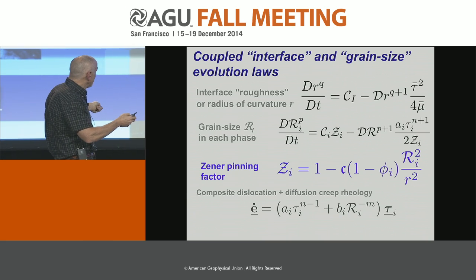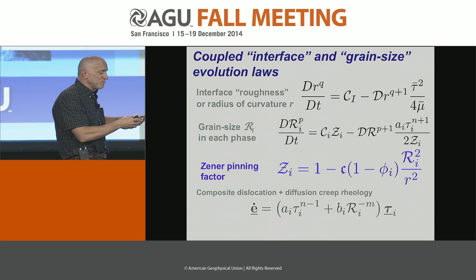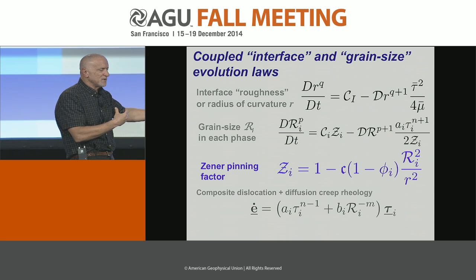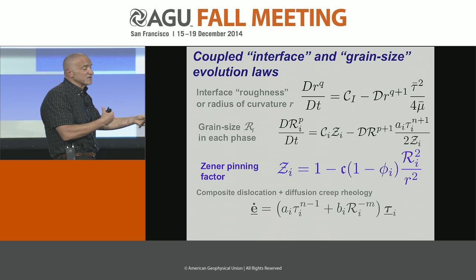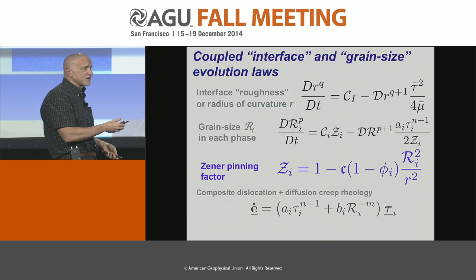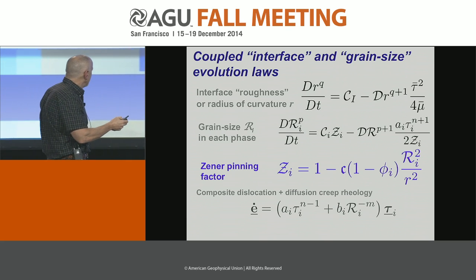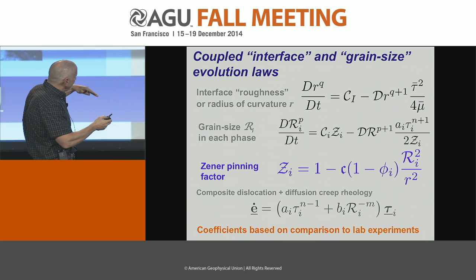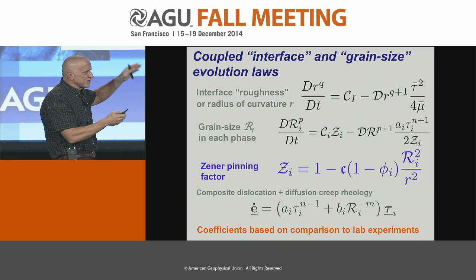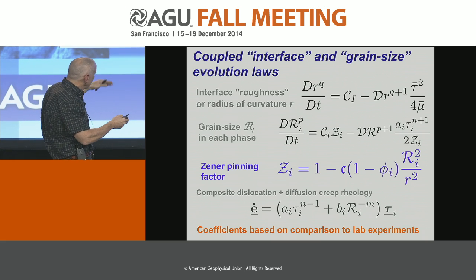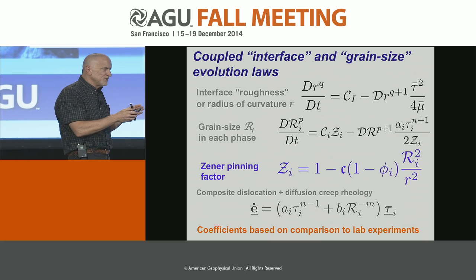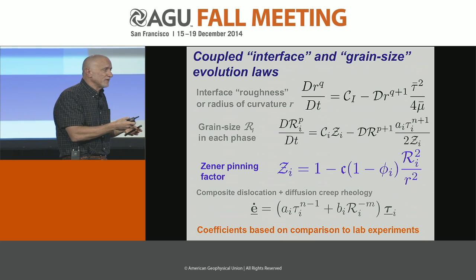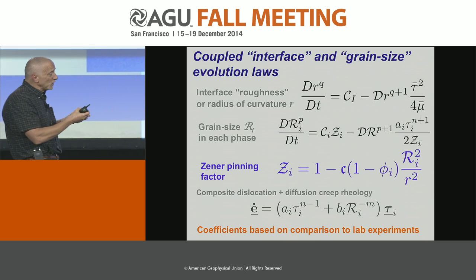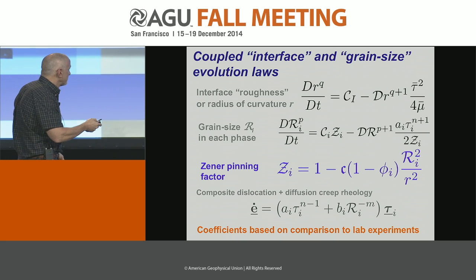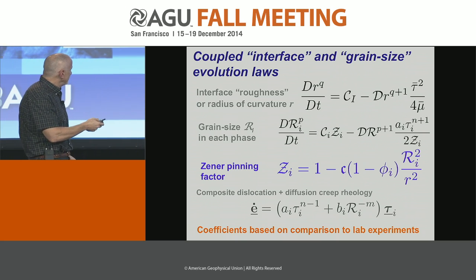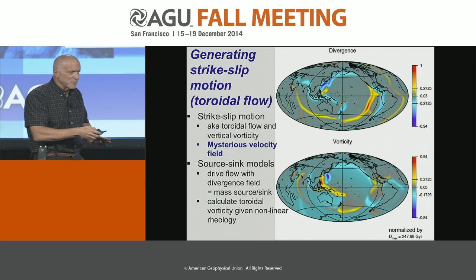So it combines both dislocation creep and diffusion creep, but done in such a way that whichever mechanism allows the fastest deformation is the one that dominates. Whichever one releases stress fastest winds up dominating. And by going through the physics at this grain scale, these various constants are related to laboratory experiments for coarsening. We could always do better, but at least it's based upon some measured values. That's kind of it for most of those equations.